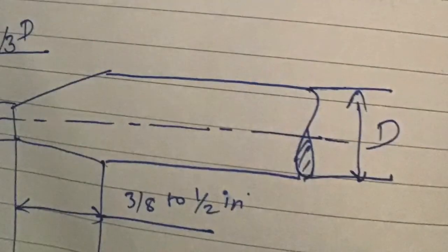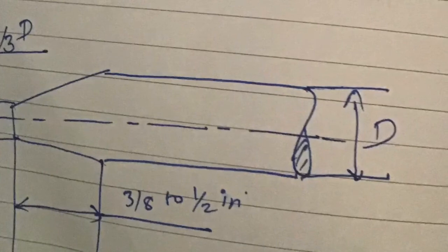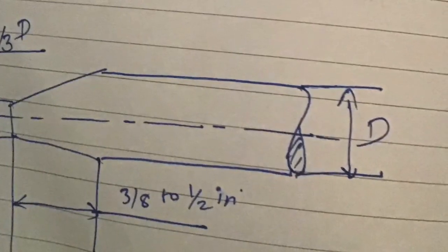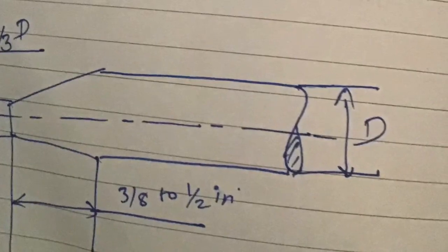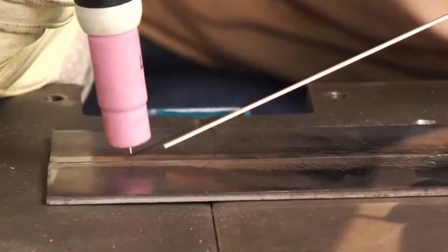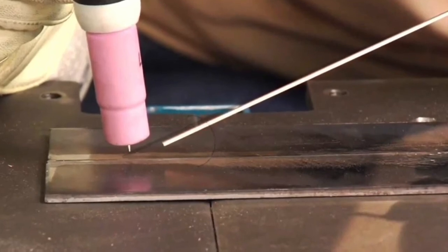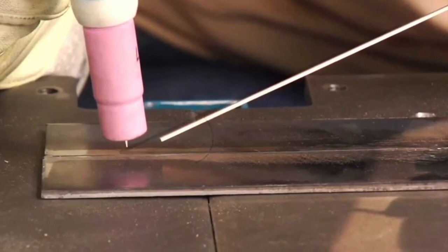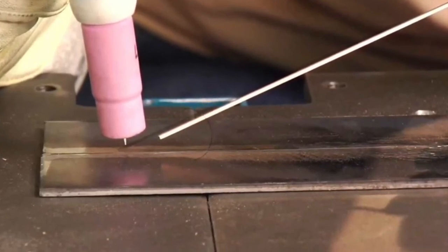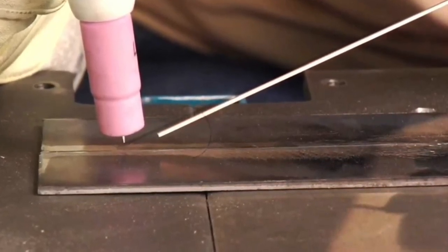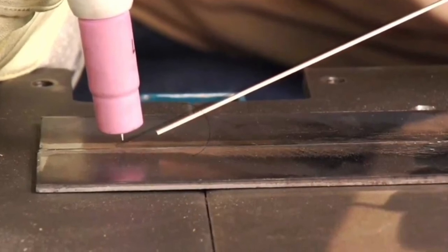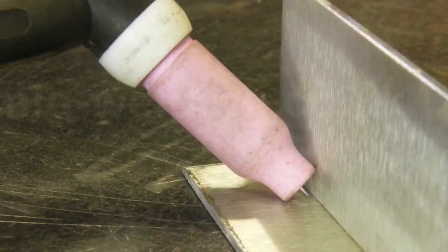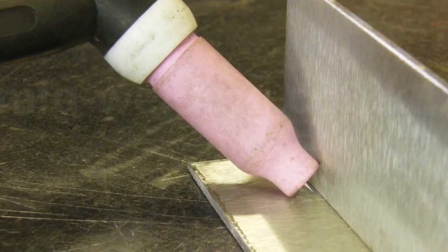This picture indicates the size of the tungsten electrode tip which is inside the gas cup. This ensures the quality of the welding. The tungsten electrode extension beyond the gas cup is determined by the type of joint being welded. For example, an extension beyond the gas cup of 3.2 mm might be used for butt joints, while an extension of approximately 9.5 to 12.7 mm might be necessary on some fillet joints.